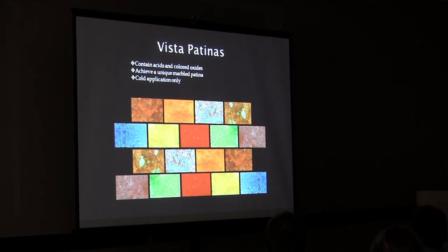Okay. This one, again, the same thing. I used the rust patina, but I didn't let it stay wet long. I dried it very quickly with a hairdryer, so you don't get very many greens going on. This right here is our mint green. On this one here, this is a little different. This one pretty much stays the mint color, and I put this on with a sponge, sprayed on, sprayed on. This one here, again, is rust and yellow, and then what happened is as it was drying, these areas stayed liquid longer, and the greens started coming up. So you have that variety.